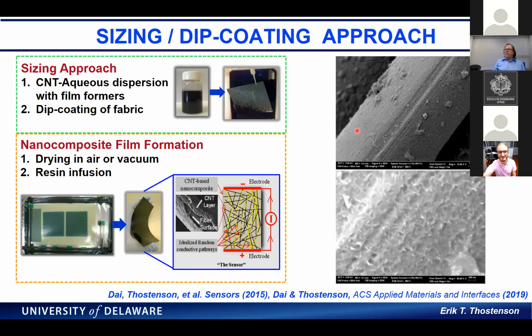Okay, so this is what we call a sizing, or maybe a dip coating process: we create an aqueous nanotube dispersion, we dip it, and then we dry it. It's a fairly straightforward process. It's difficult to control, but you do see a pretty dense coating, and you can control that using the chemical functionality. You can control not only the volume fraction, but also the adhesion with the surface of the fibers. And we've used this quite a bit in our research as well.